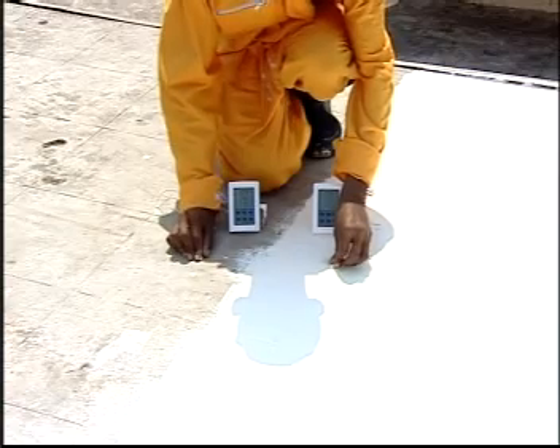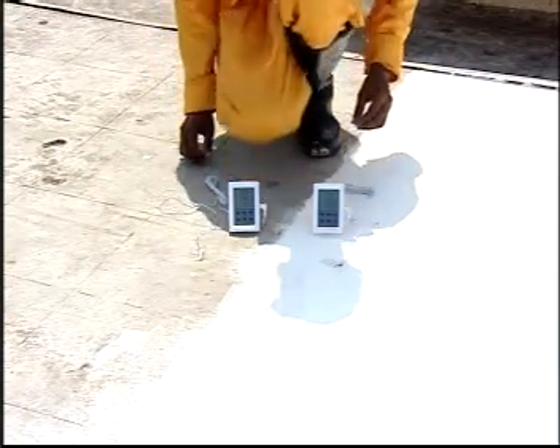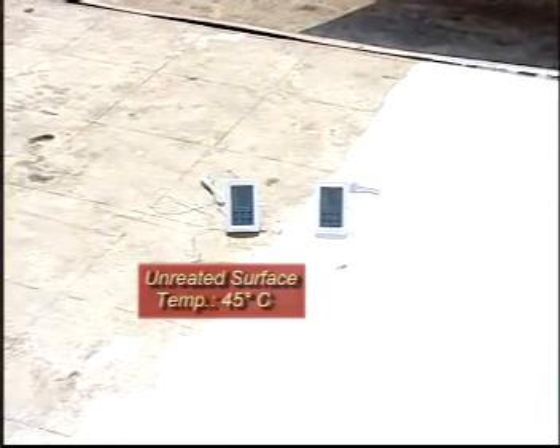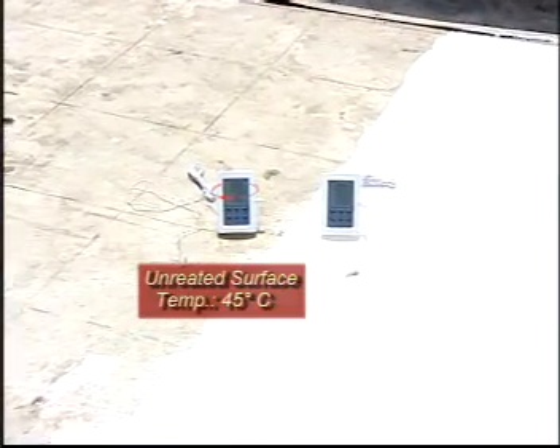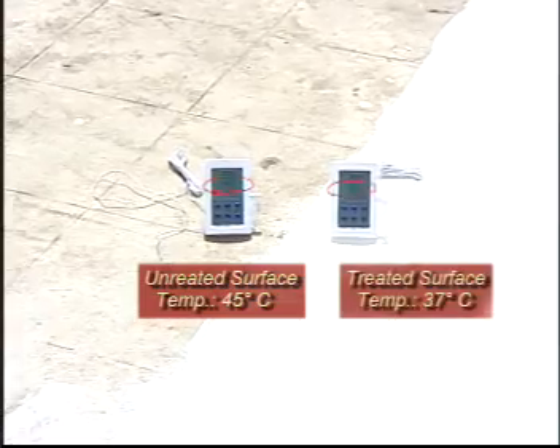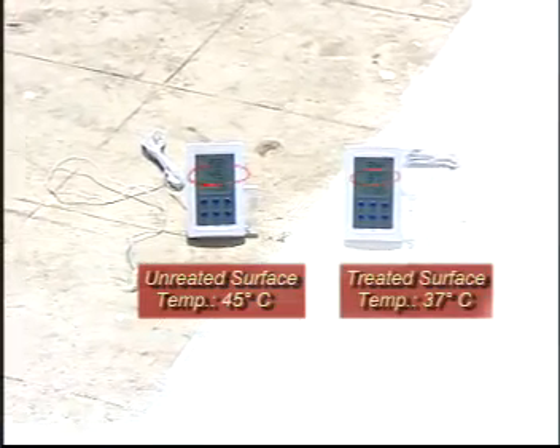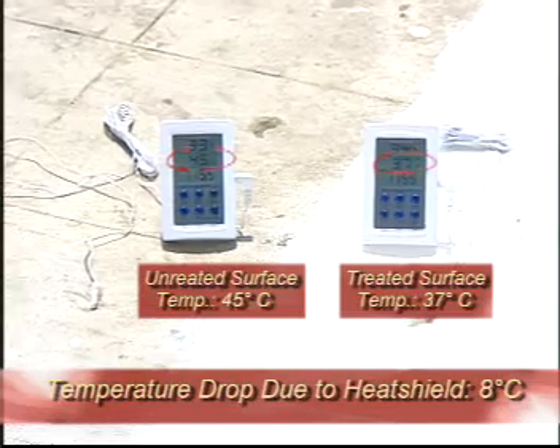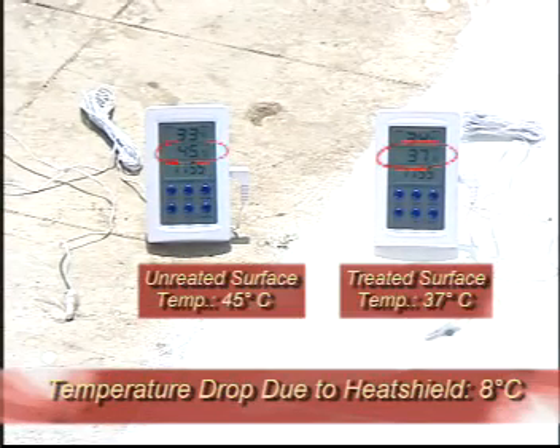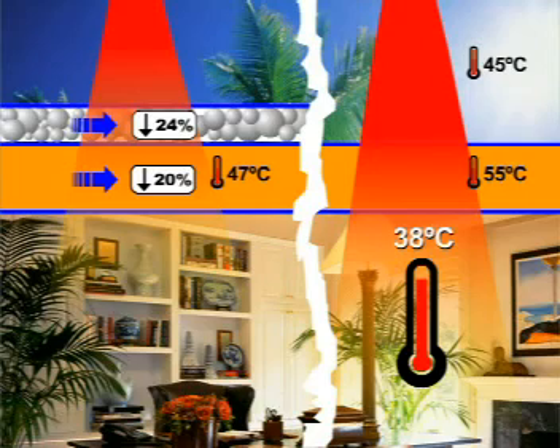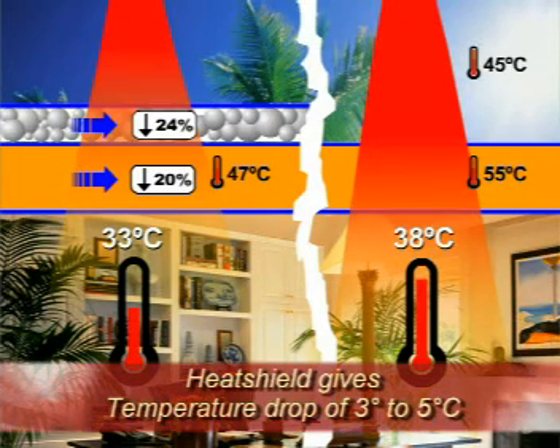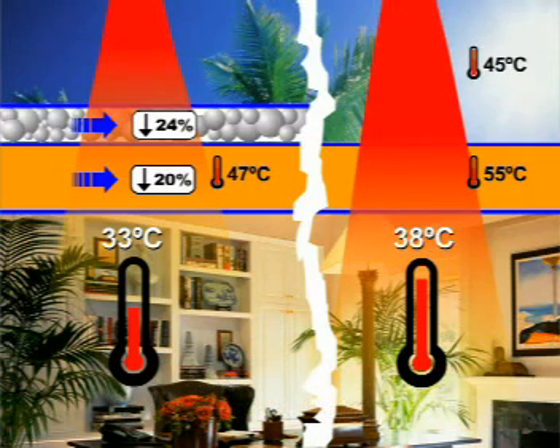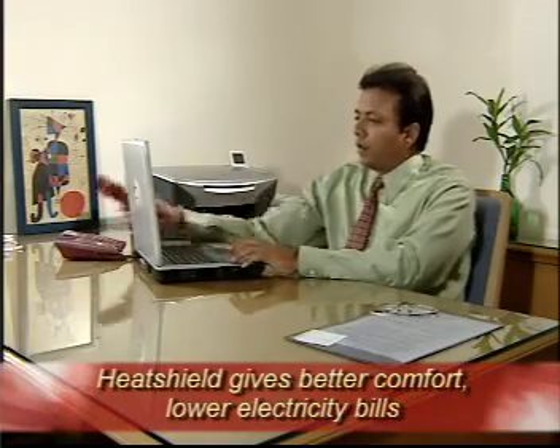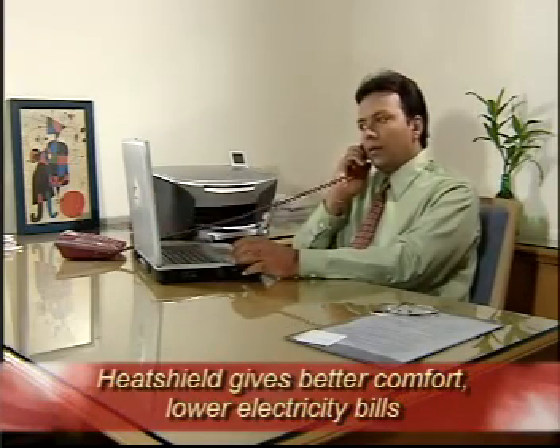Similarly, on a concrete roof, the untreated surface on the left side has a temperature of 45 degrees Celsius, while the application of Heat Shield on the concrete has resulted in a surface temperature of only 37 degrees Celsius, giving a surface temperature drop in concrete of 8 degrees Celsius. Due to the application of Heat Shield, the temperature inside the room is also lower by 3 to 5 degrees Celsius compared to the inside temperature in a room without Heat Shield. This results in comfort and also in lower bills for air conditioning.